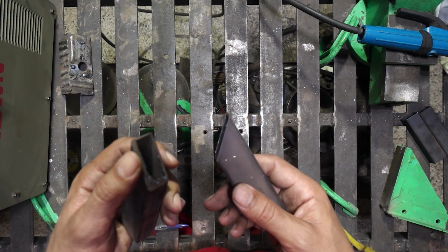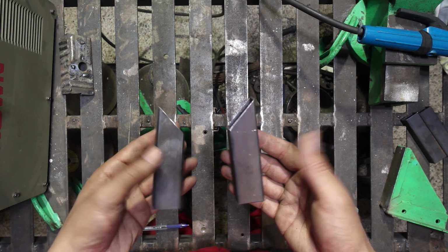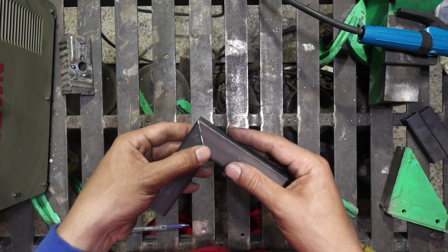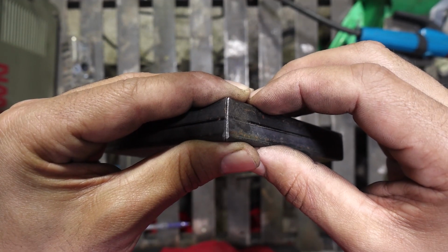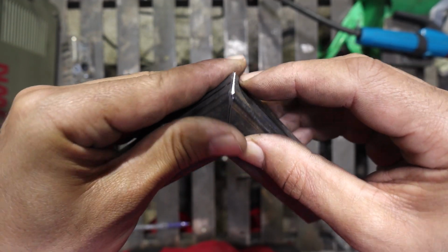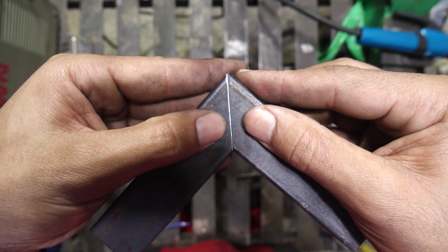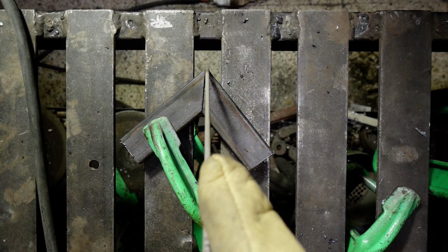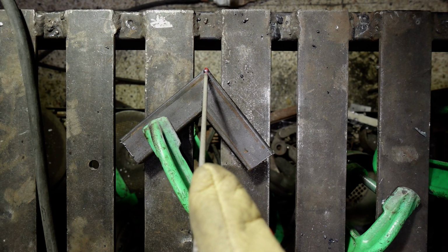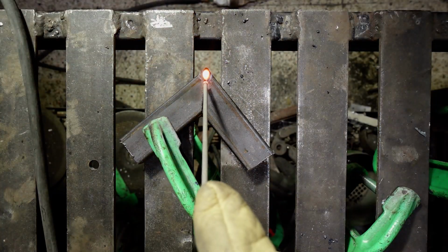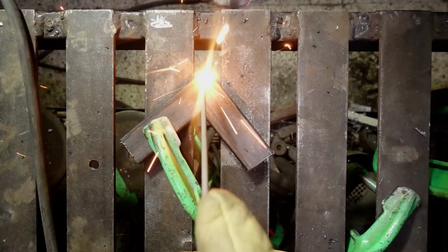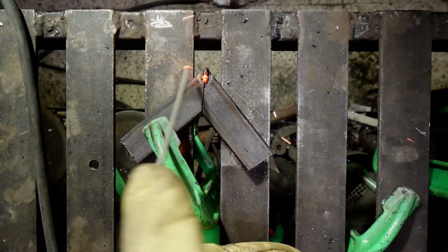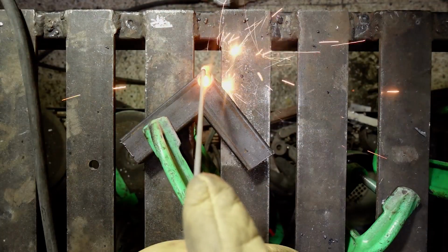I will weld these two pieces that I cut at 45 degrees with a thickness of 1.2 millimeters. I am welding and stopping, and do that until the end of the weld. The reason for that is to let the piece cool down a bit, because if I try to weld a continuous weld here, I will put more heat on the piece, more than it can handle, and it will melt, making a hole in it.